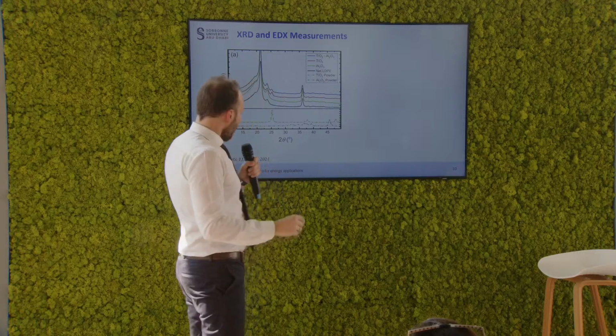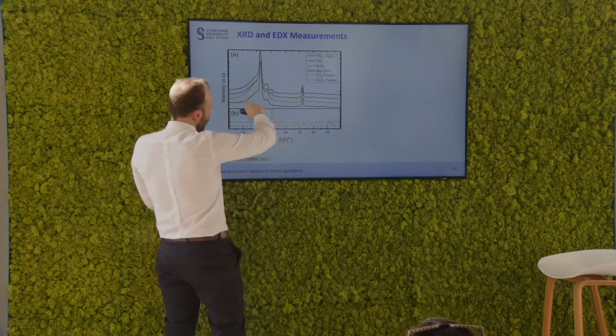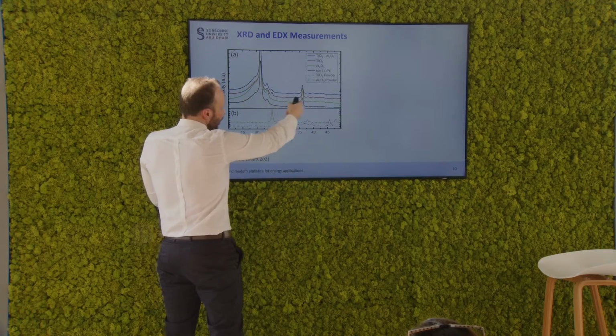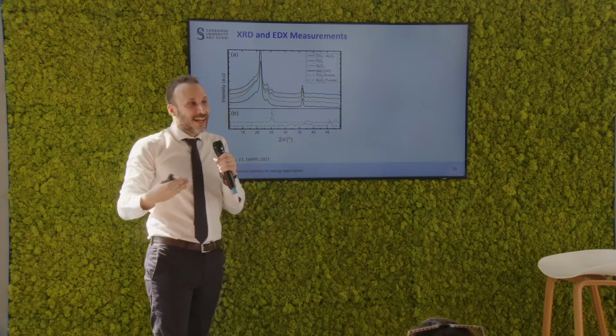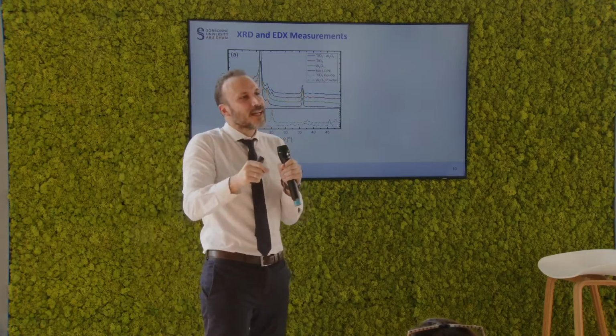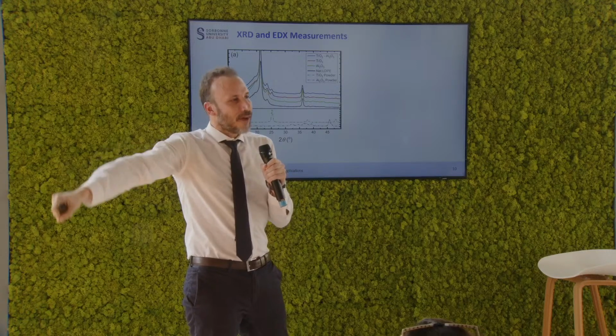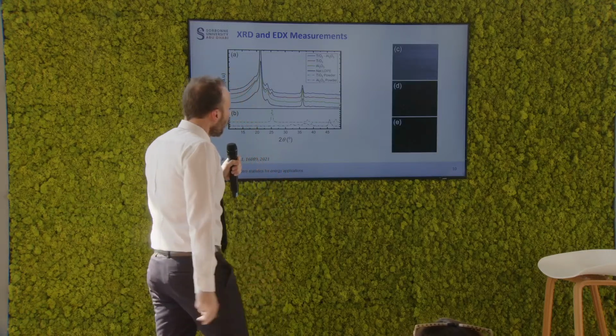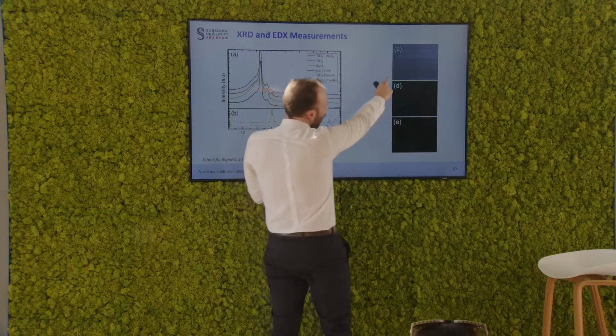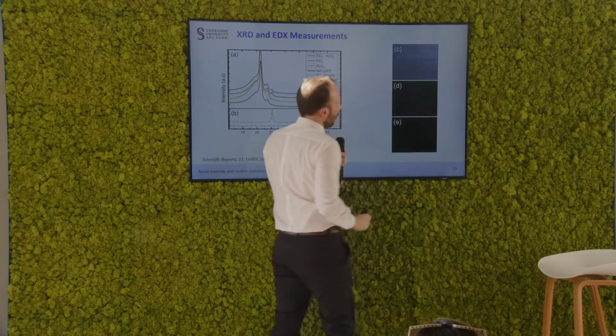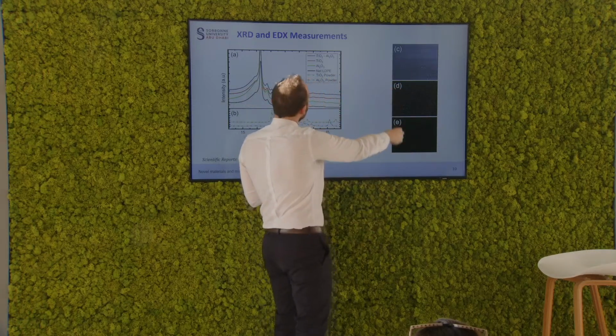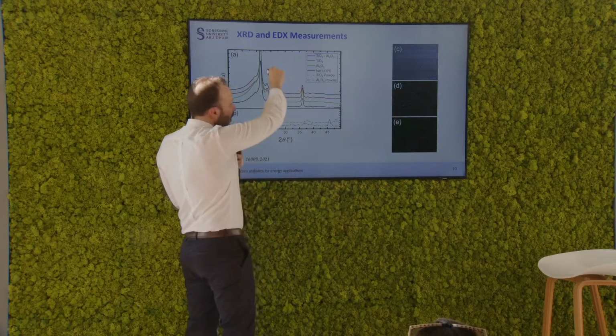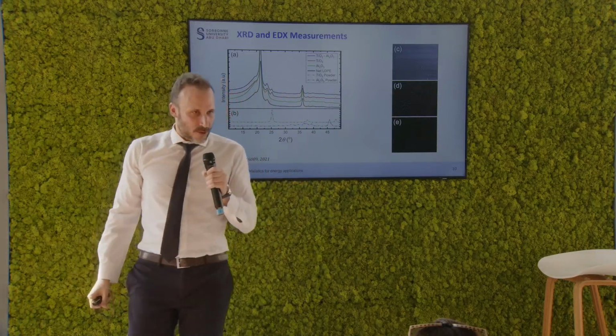Moreover, it is the sharpness of these peaks, whether they are more round like this or more sharp, that allows us an initial estimation of what is actually the particle size in the final material. If you follow me to these measurements here, this is simply how the film looks like in an SEM image, but in images D and E, we are basically conducting energy dispersive X-ray measurements.